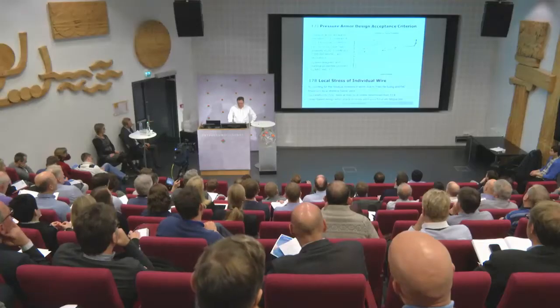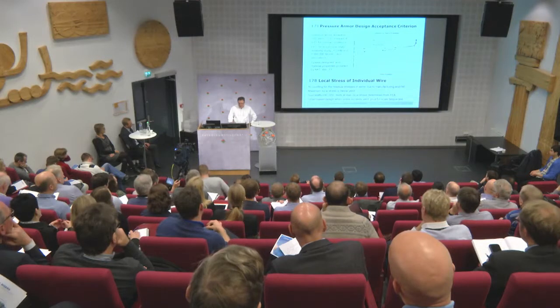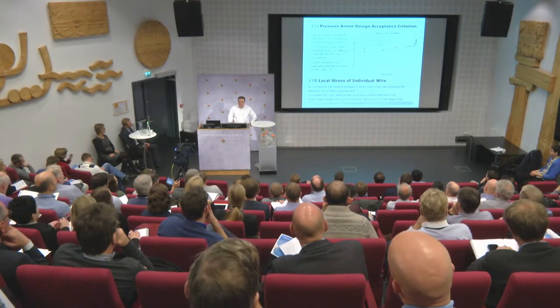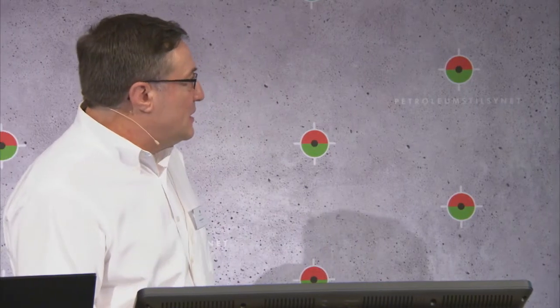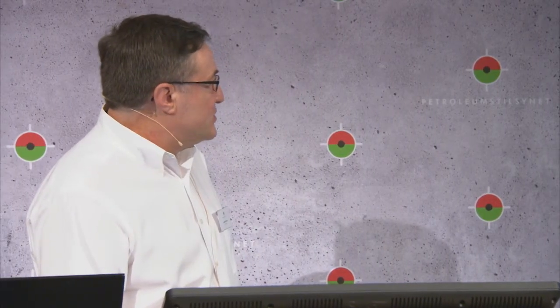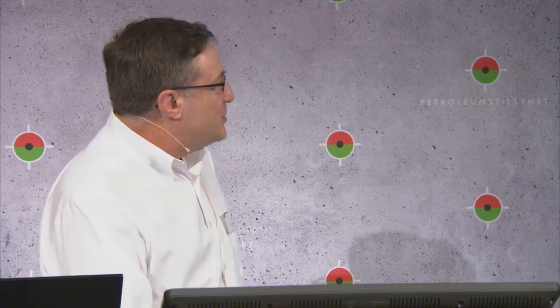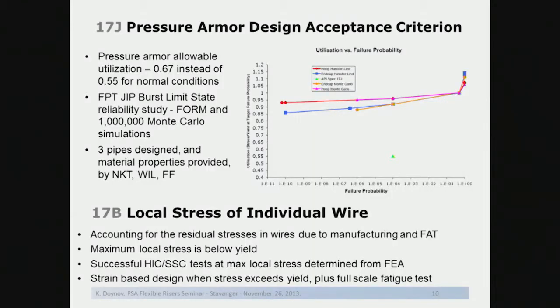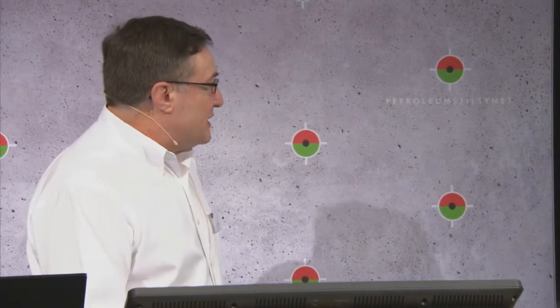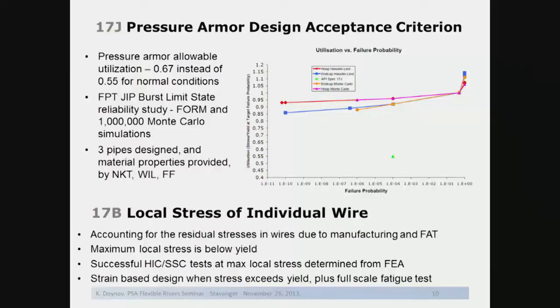Another addition is recommendations on local stresses for individual wires. They are non-existent at this time in the current version of 17J and B. We included that in the upcoming version of 17B. So the first point is that we need to account for residual stresses in wires due to manufacturing and FAT, which is very important when you account for fatigue life calculations, especially on the hoop strength layer. We have a recommendation to keep the maximum local stress in a wire below the yield.